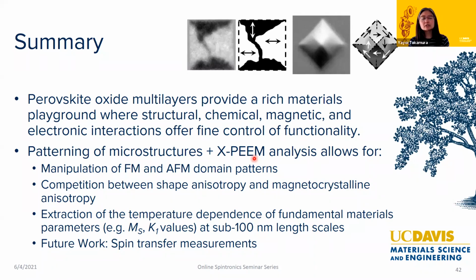Especially in our case, with the way we pattern them, they not only become amorphous, they become insulating. So we have this really crazy insulating matrix, which can sometimes distort our images. If you're just looking at those ridge features, you might be better off and have better spatial resolution than what I have. We've been able to say 100 nanometer spatial resolution for complex oxides that we pattern this way, but within metallic systems, they can get to smaller, maybe tens of nanometers.